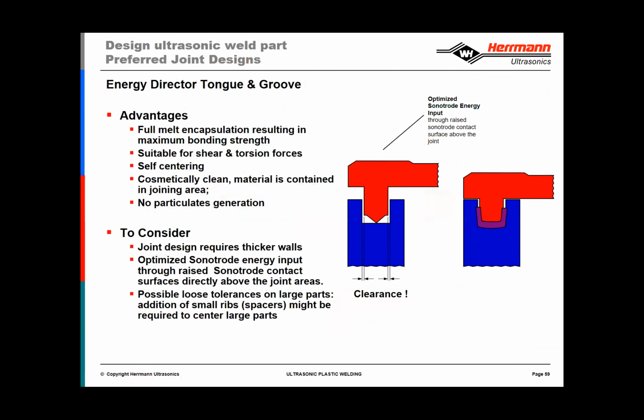The energy director tongue and groove is really the go-to. This is, whenever possible, the primary recommendation that we make. You'll notice that the tongue is fully contained within the groove, so the melt now not only bonds on 2 surfaces, but hopefully bonds on 3 surfaces. So mechanically, there's an advantage.